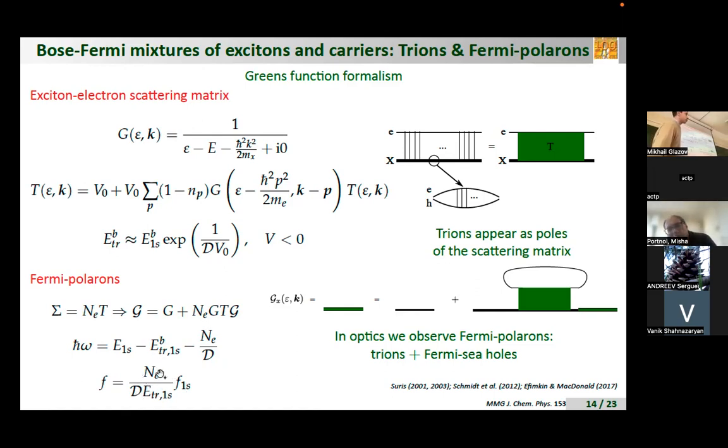There's another factor that can be converted to the trion radius squared. But sorry for interrupting, that's interesting. I'm just trying to understand. So if we have a shallow Fermi sea, this hole that remains may only have a relatively low wave vector, so it is quite delocalized. And probably that is why it plays no role. Exactly, yes, that's the physics, exactly. And then it plays no role.